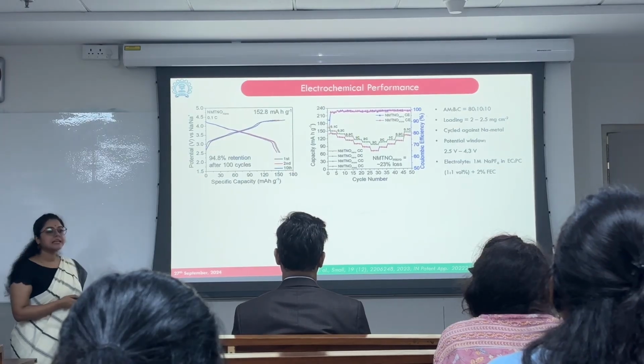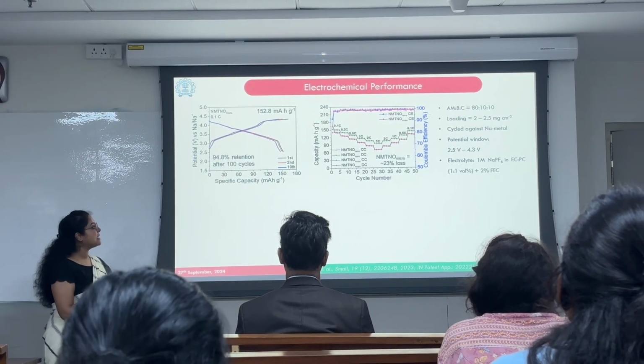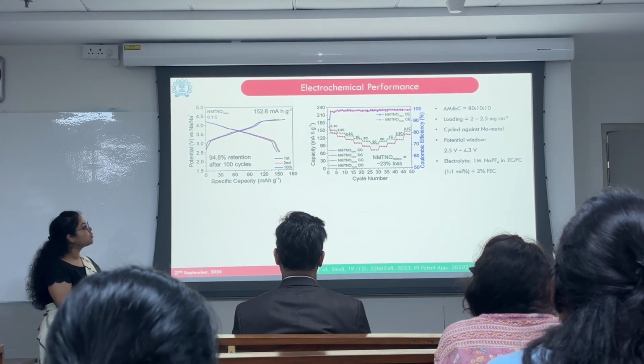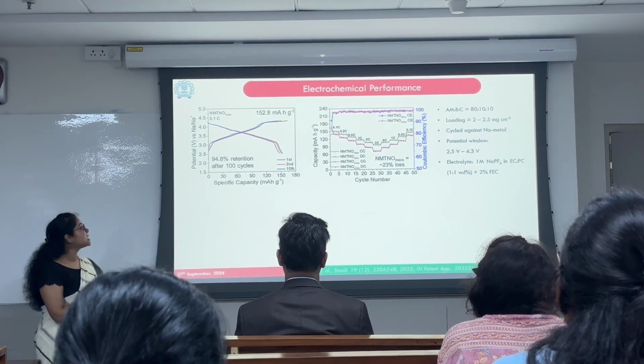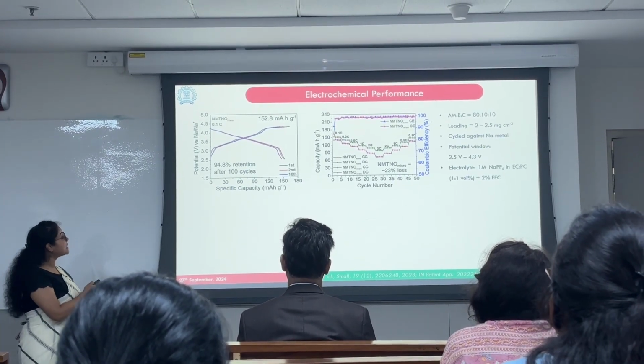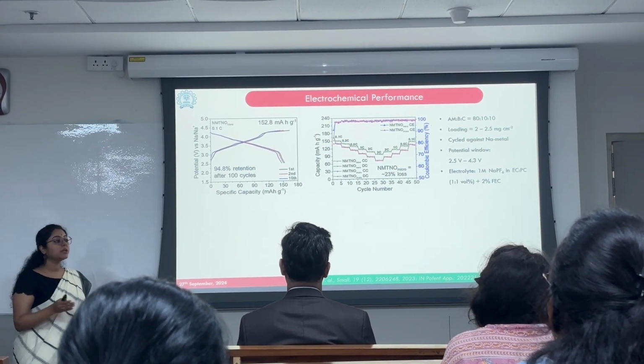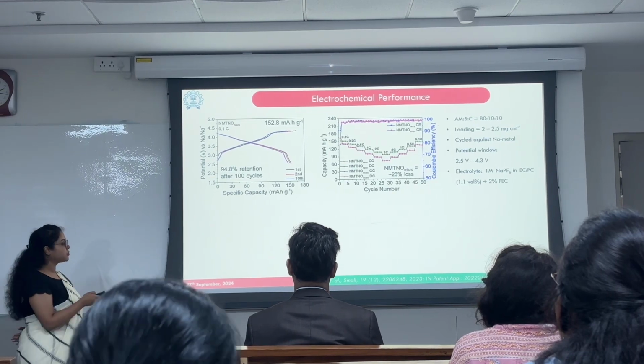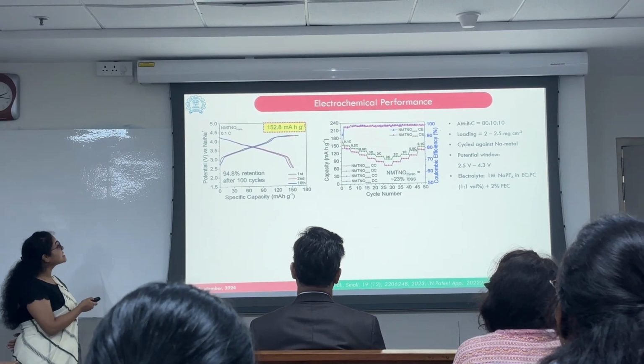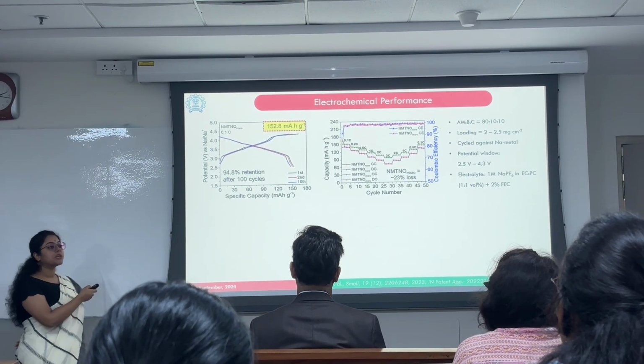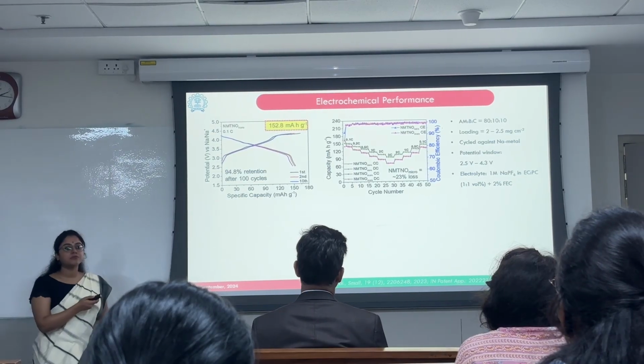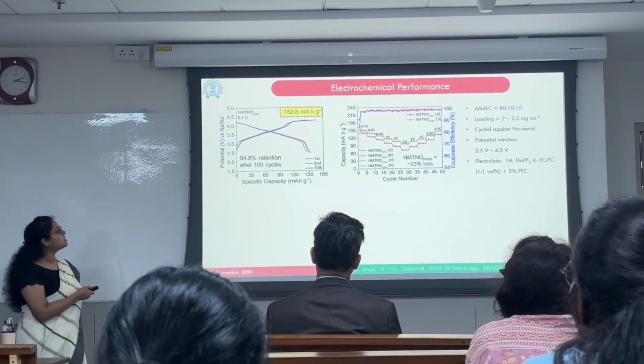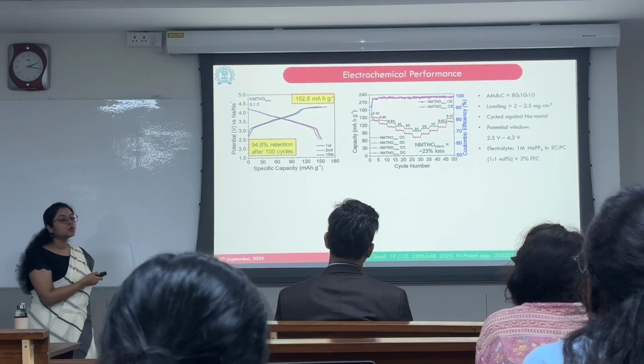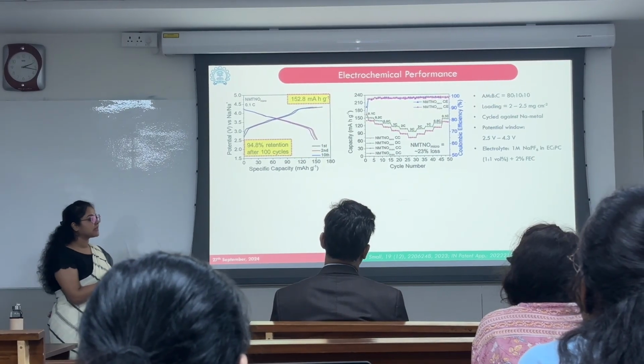We then tested the electrochemistry against a sodium cell and cycled it within a potential window of 2.5 to 4.3 volts. At a current rate of 0.1 C, both the NMTNO nano and micro gave us a similar voltage profile. However, the capacity obtained from NMTNO nano was much greater, around 153 milliamp hour per gram, with a capacity retention of more than 94% after 100 cycles.